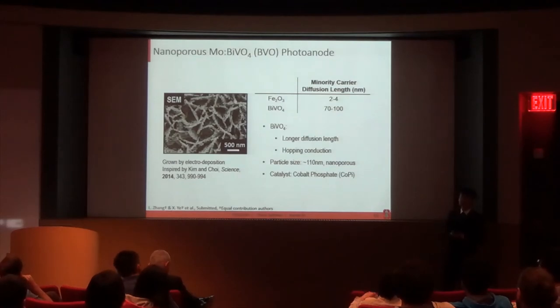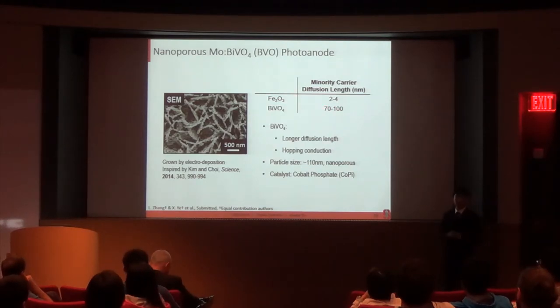And this material is bismuth vanadate with some molybdenum doping. We chose this material because, first, the minority carrier diffusion length in bismuth vanadate is much longer than in iron oxide. And second, it also exhibits a hopping conduction mechanism, which indicates that the carrier mobility can be strongly activated with thermal energy. And in order to collect as many carriers as possible, we synthesized this nanoporous bismuth vanadate by electrodeposition. The particle size is around 110 nanometers, which is only slightly larger than the diffusion length.